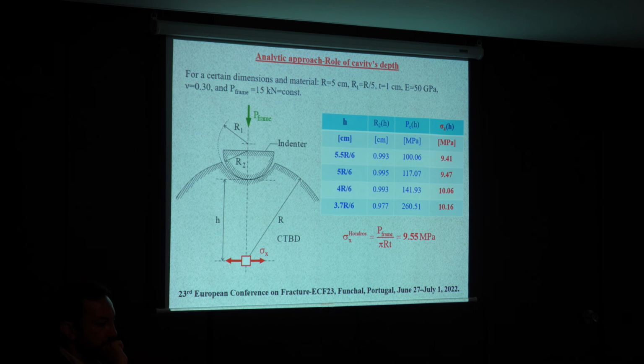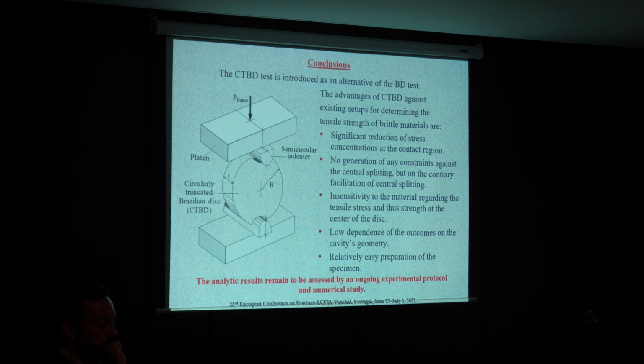So, coming to an end, we believe that this geometry, which is relatively simple, not as simple as the one introduced by Carneiro, because we should groove somehow the specimen, seems to cure the main drawbacks of the previous proposal. What are the drawbacks? Severe stress concentration and the role of the material. The theory is now available.